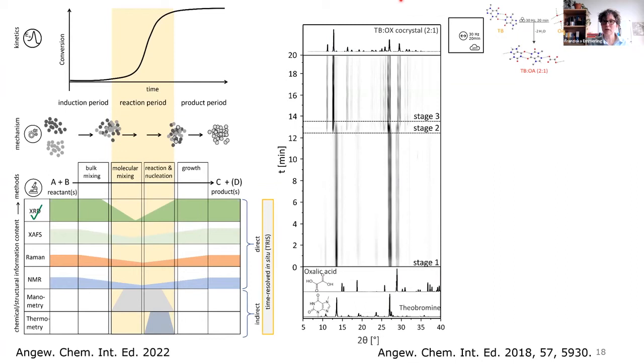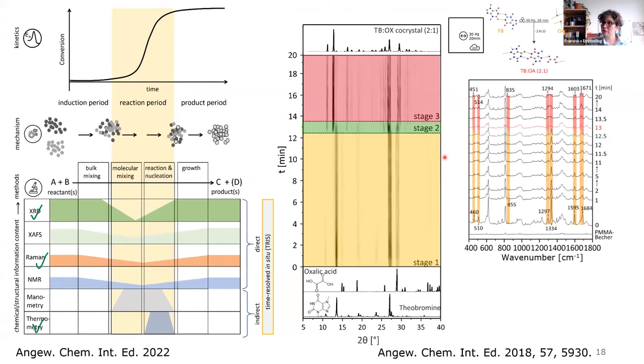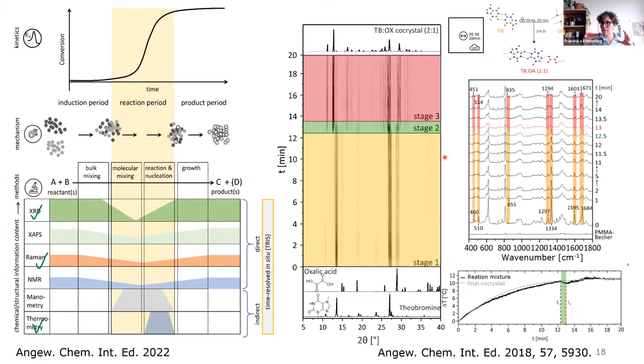And here's an example. Again, you see it's a co-crystallization, a 2-to-1 co-crystal. In this case, it's theobromine and oxalic acid. We see a normal reaction pattern. We have this induction period, we have a reaction period, and the product stage. And luckily, if you combine different methods, which we have done with Raman spectroscopy shown here and also thermography, then you can really see the process both in the changes in the local molecular ordering, as well as in the crystallite size, and you get information about the temperature. Here you can see the temperature of the reactant mixture in black, and in gray we have the temperature of the final product milled under the same condition.